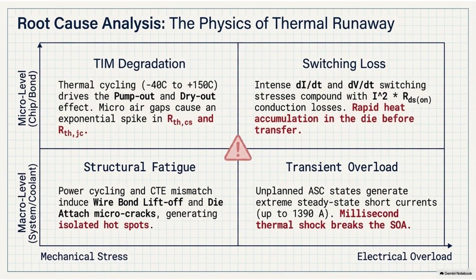Wow. You have ultra-thin aluminum or copper wire bonds connecting the top of the silicon die to the circuit board. And these wires are carrying hundreds of amps. Yes. And as you push huge amounts of power through this system, over thousands of driving cycles, active power cycling, the silicon die and the copper wire are expanding at different rates. They're literally fighting each other at the weld joint. So the weld is being sheared back and forth. Continually. And eventually, the metal fatigues. The microscopic bonds begin to crack and sever.